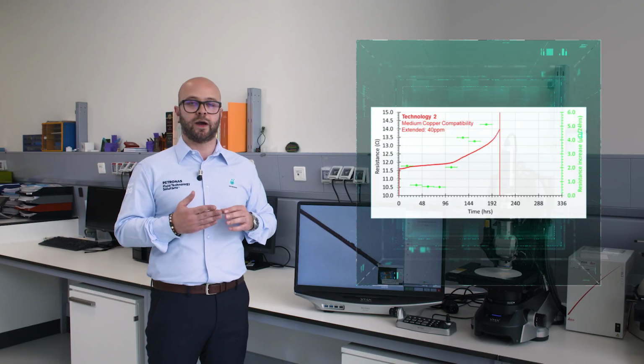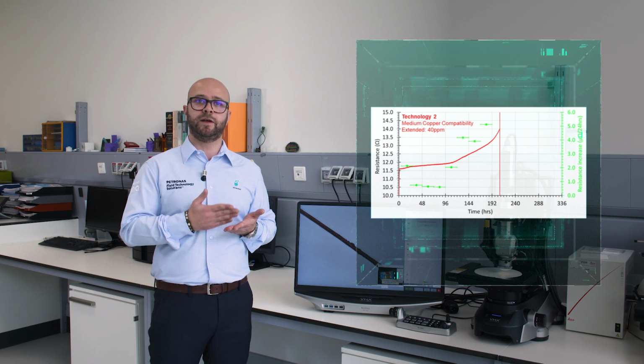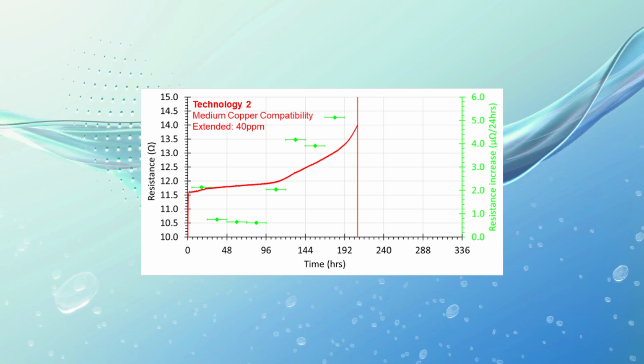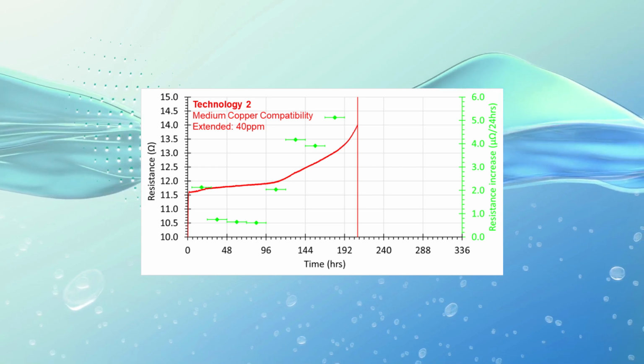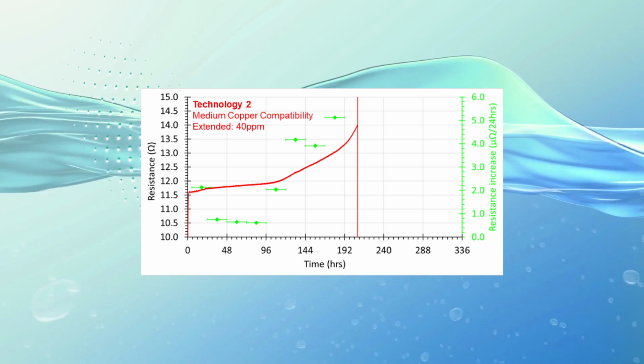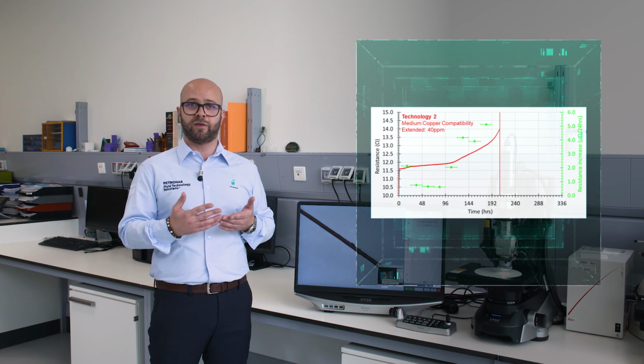These increases for the whole length of the test until we reach the breaking of the wire. It's important to highlight that 192 hours is a good result compared to the previous generation that were reaching barely 20 hours of resistance in this test. Situation gets completely different when we move to technology 4.